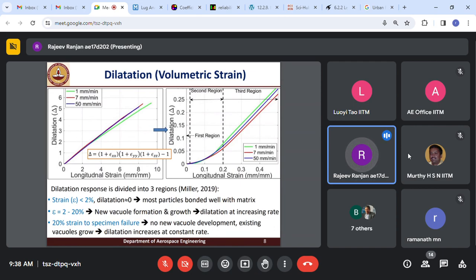We determined the dilatation during the uniaxial tensile test, and this finite strain dilatation formula is used for that. This response here shows the dilatation response up to the failure, whereas this is the zoomed in view of the dilatation up to 50% strain.